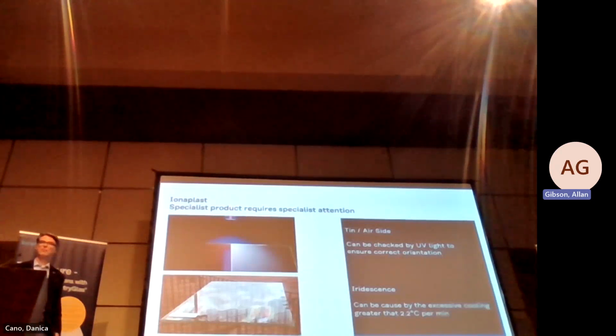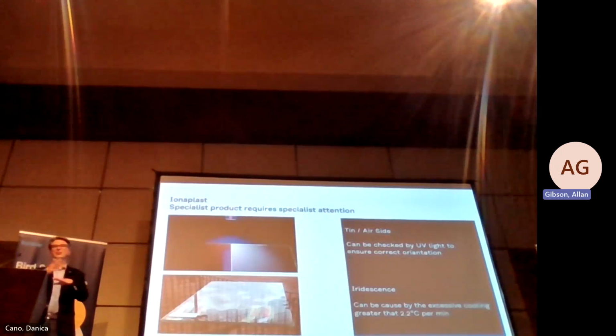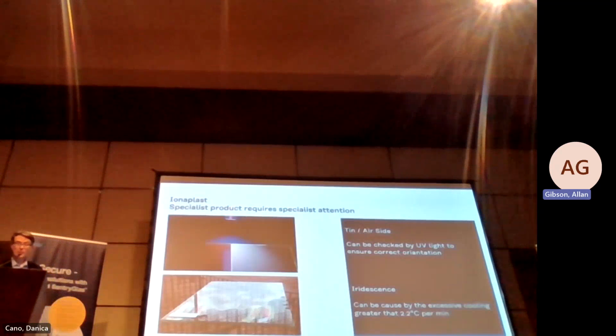When it's floating over a tin bath, that's when you get the nice smooth float glass, as it's commonly known. The side that's on the tin is known as the tin side, and the side that's not on the tin is called the air side. Now, when you're laminating SentryGlass, you should laminate with tin side, SentryGlass, tin side. So you've got the two air sides on the outside.